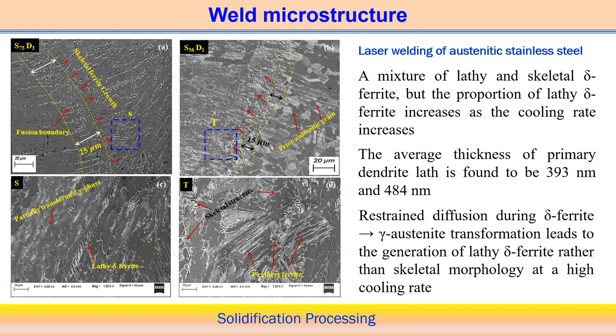Prior austenitic grain also, this is the prior austenitic grain, marked here by the arrow mark. So the gamma phase, the austenitic phase, is partially transformed, not fully transformed. All this mixture of structure is what we actually get in the actual welding process, and this happens because of the variable cooling rate we see during the welding process. At different positions the cooling rate varies, so based on that we can get a mixture of different structures, and their morphologies are different. Okay. So overall you can see that in the case of laser welding of austenitic stainless steel, we get a mixture of the lathy type as well as the skeletal delta ferrite.